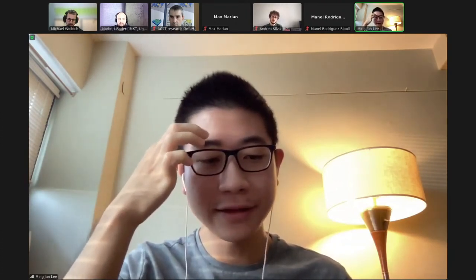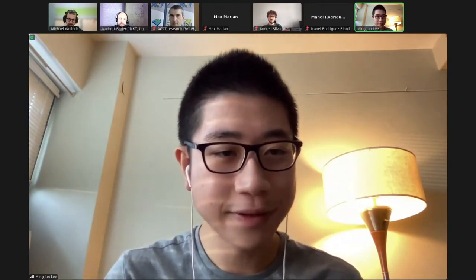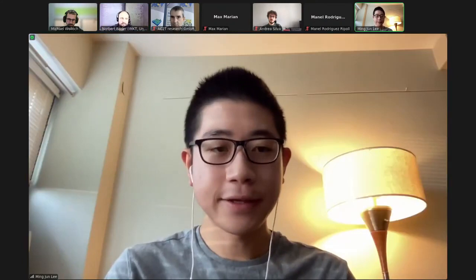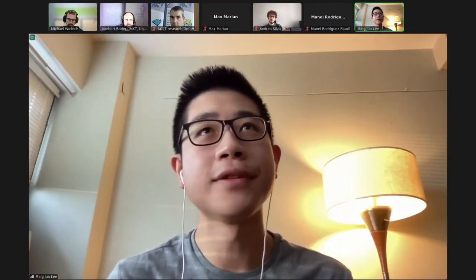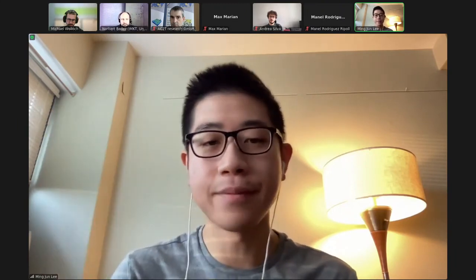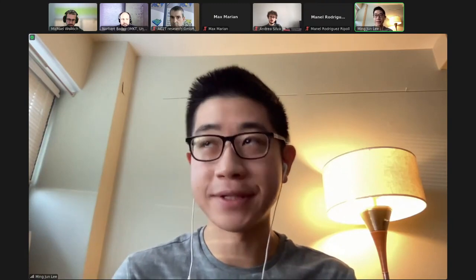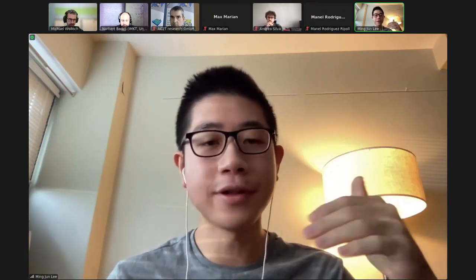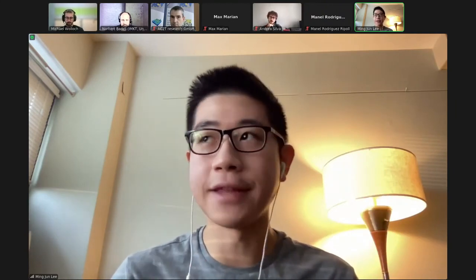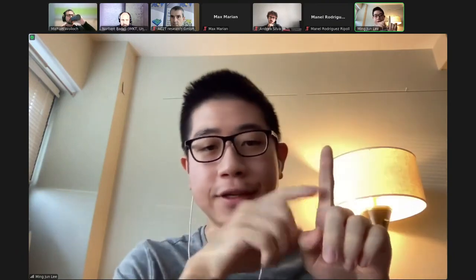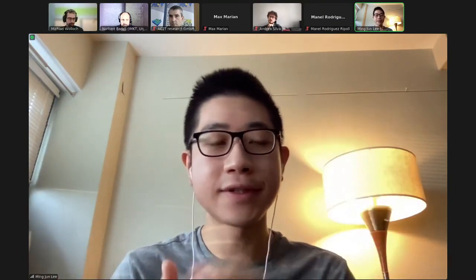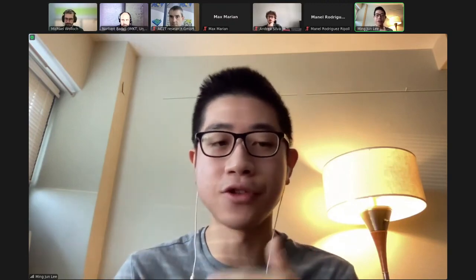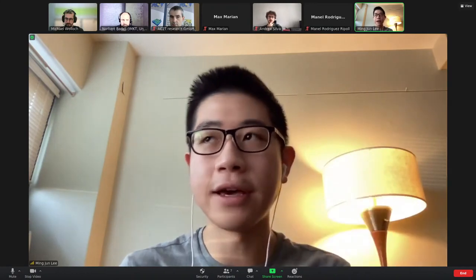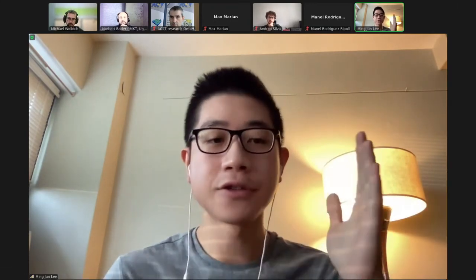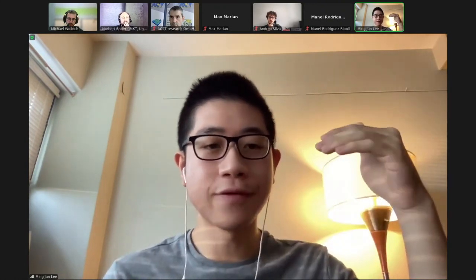And regarding the second, you mentioned calculation of the friction properties. Yeah, is there a model to predict it? In 2018 and 2020, one of my seniors in the lab, Tuba Shoaib, who has already graduated, studied specifically the physics of friction on polyacrylamide hydrogels. What she showed was that there is actually a U-shaped relationship of friction against the sliding velocity. So at slow sliding velocities, the adhesive interactions between your gel and your measurement device, in our case the AFM tip, are the predominant contribution to the friction force. So as you increase the sliding velocity, the friction force actually decreases.